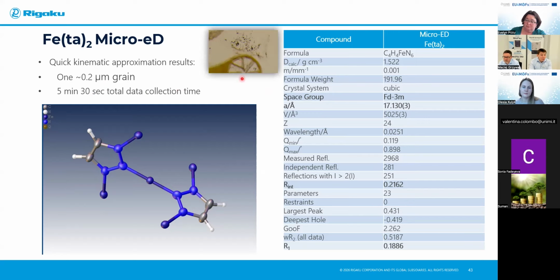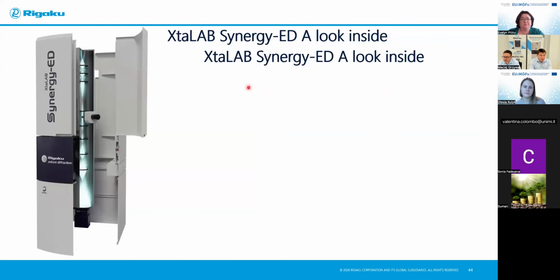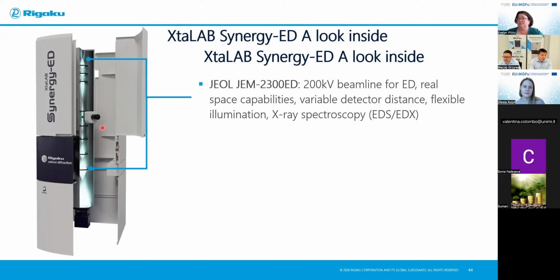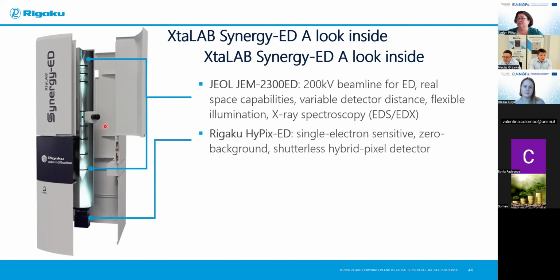So as I took the picture, I tried to do it with X-rays, but as you can see, the powder from here was really, really fine, and there was no option to do it with X-rays. So we have a new instrument, which is called XtaLAB Synergy-ED. It's still part of the Synergy platform, but as you can see, it looks completely different and not like typical X-ray diffractometers, because inside we have a beamline delivered by JEOL, our partner, which built us a beamline for electron diffraction. And we're using our own design and the best detectors, HyPix direct photon counting detectors.